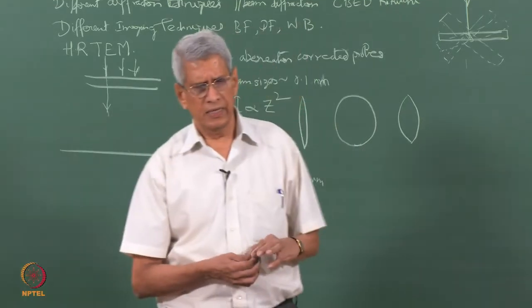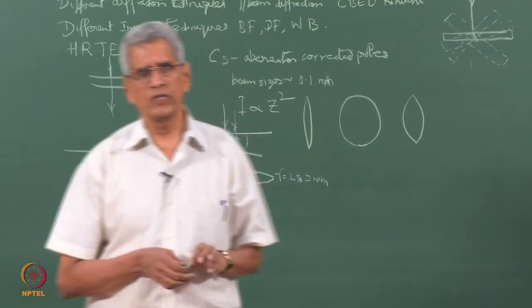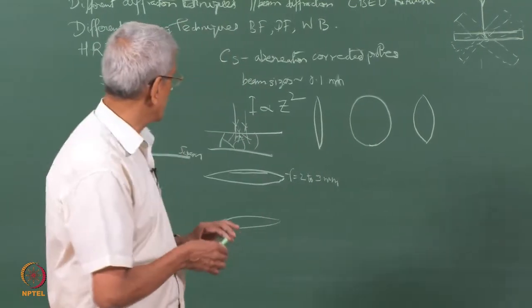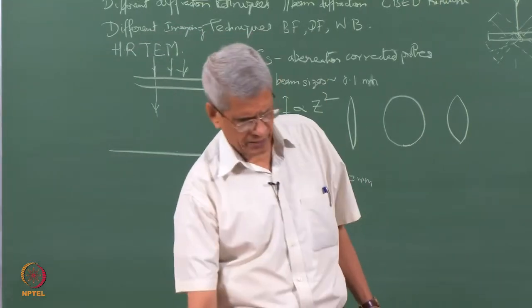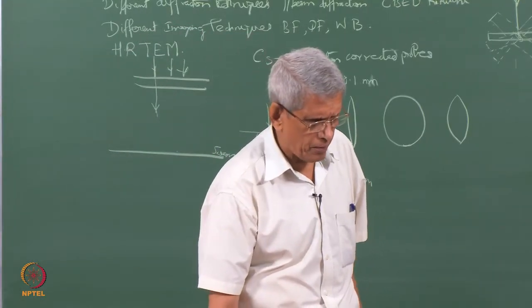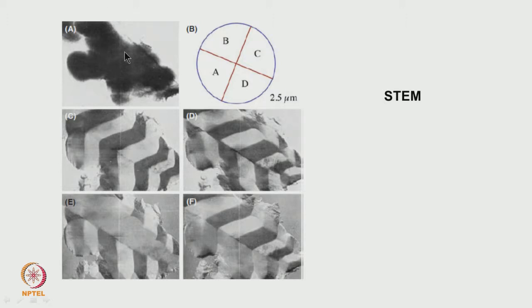Okay. That is what we talked about in a conventional transmission electron microscope. In a scanning transmission electron microscope also, we can make the beam scan on the sample surface. Depending upon the direction of the magnetic field in different domains, the electron path will be changed accordingly. So, they will be coming in different directions when they come out of that sample surface.